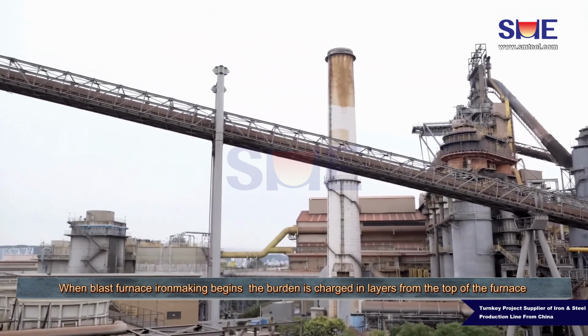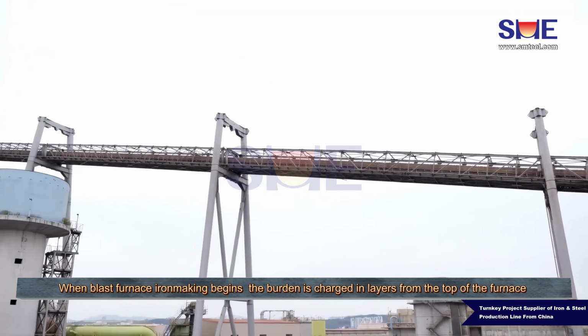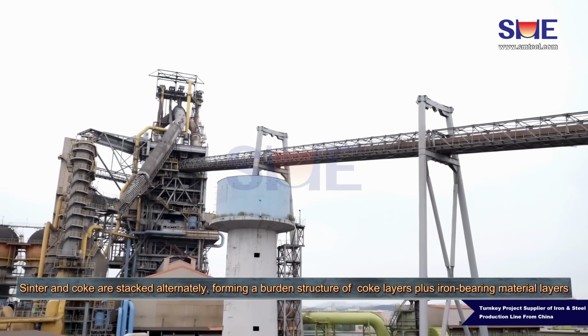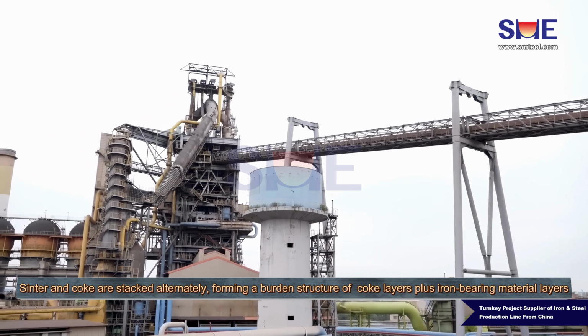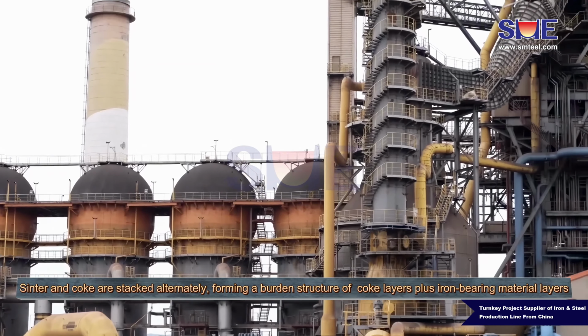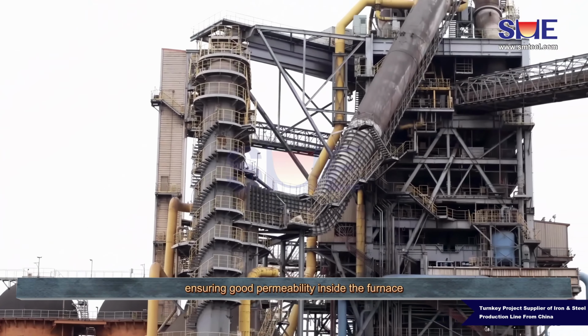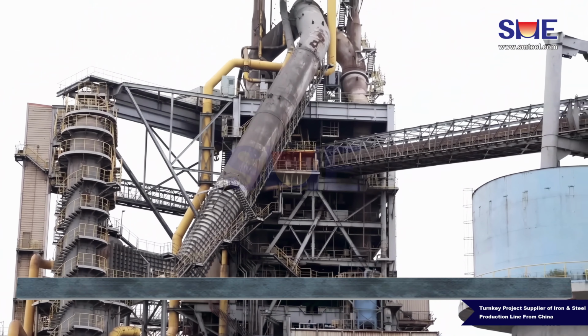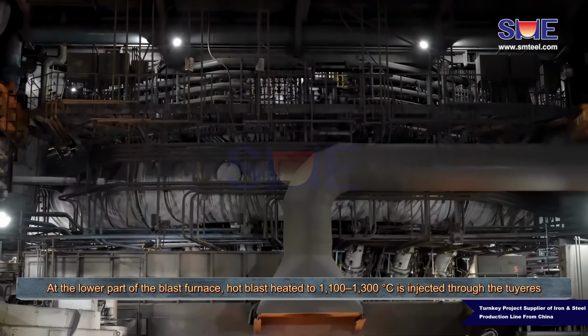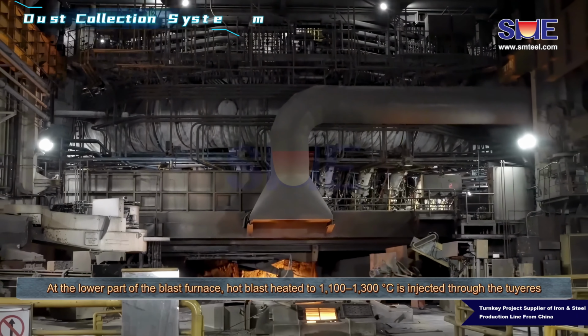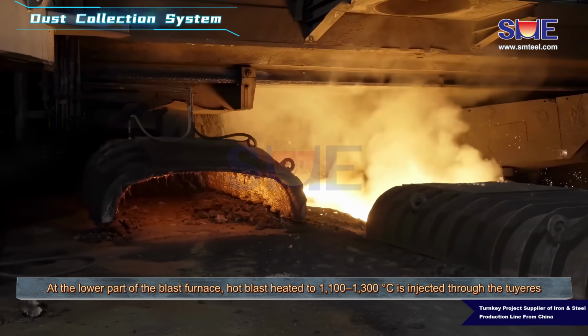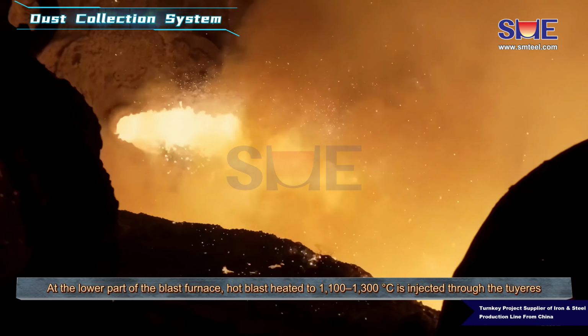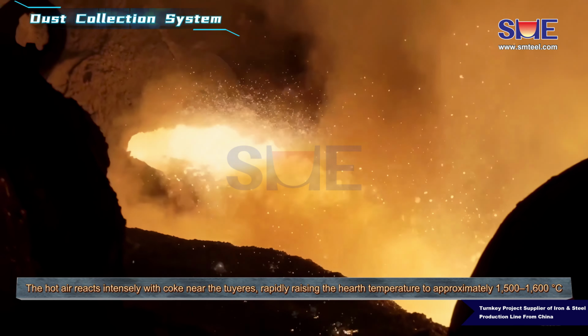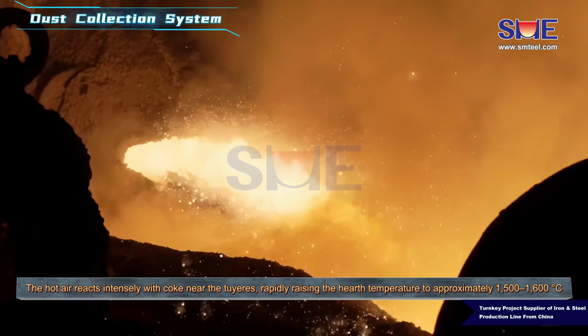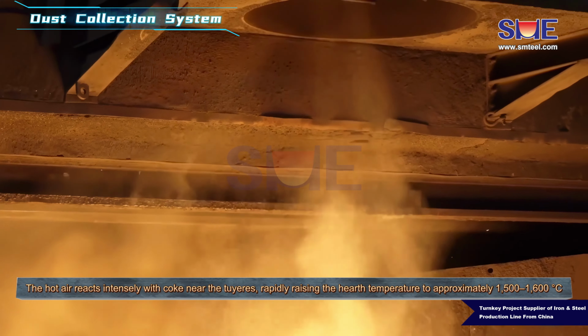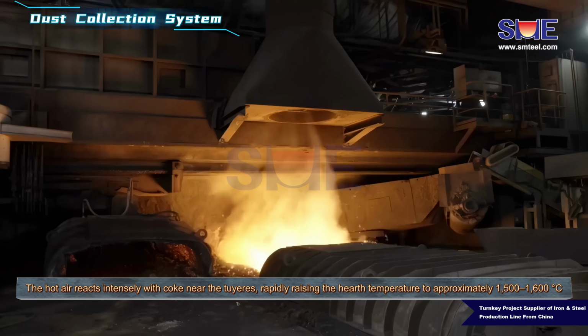When blast furnace iron making begins, the burden is charged in layers from the top of the furnace. Sinter and coke are stacked alternately, forming a burden structure of coke layers plus iron-bearing material layers, ensuring good permeability inside the furnace. At the lower part of the blast furnace, hot blast heated to 1100 to 1300 Celsius is injected through the tuyeres. The hot air reacts intensely with coke near the tuyeres, rapidly raising the hearth temperature to approximately 1500 to 1600 C.